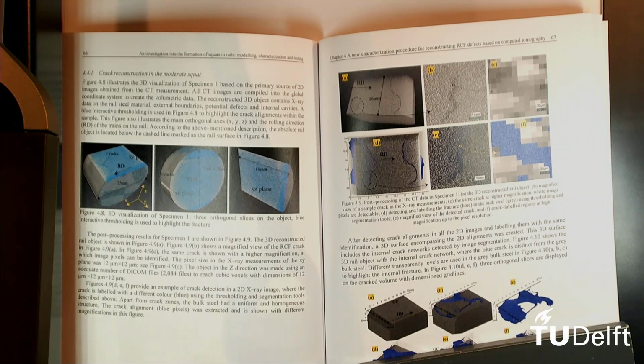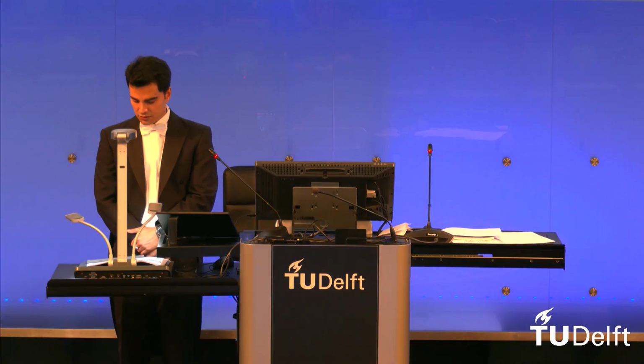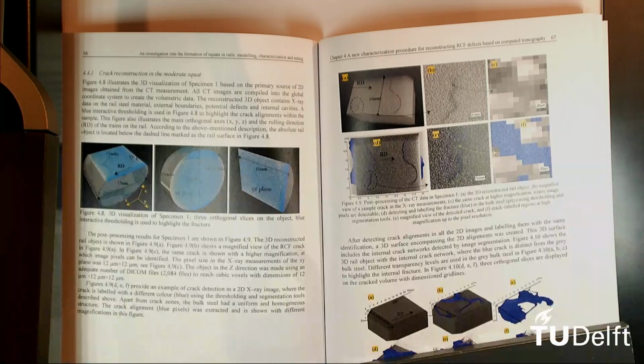This has to do with the difference in the diffraction morphology of the 2D images. The steel material by itself has a very homogeneous microstructure. So if you see any dark area inside the steel, it might be either inclusion or crack. This is my general understanding. So with any dark area, in this case black area, you might have some estimations about the presence of crack.